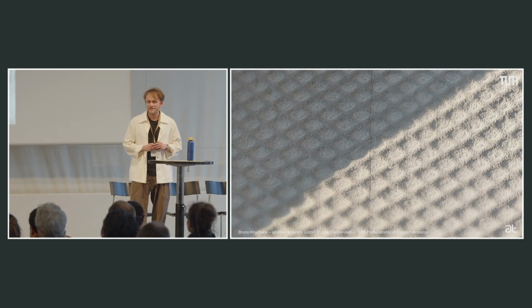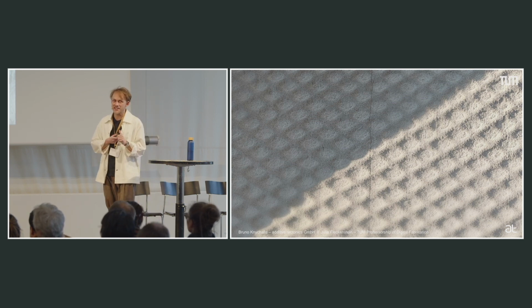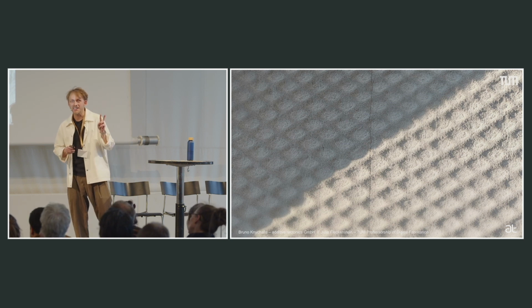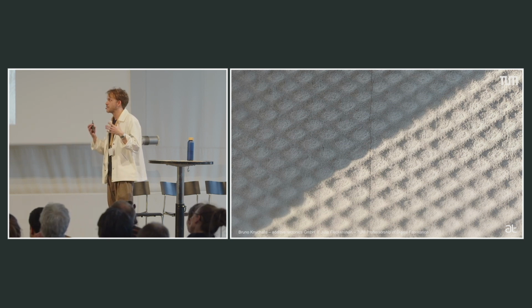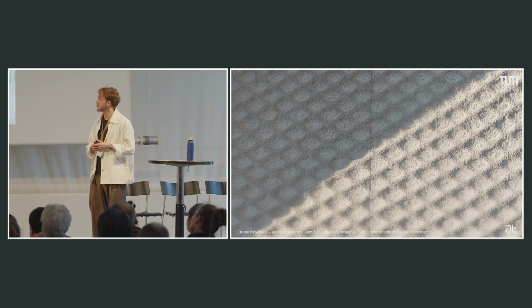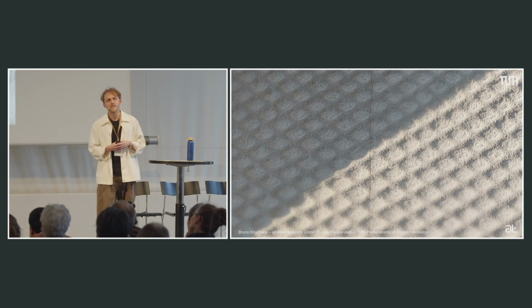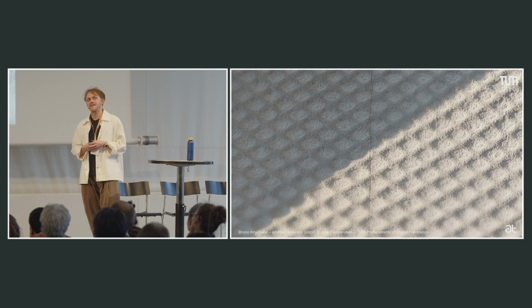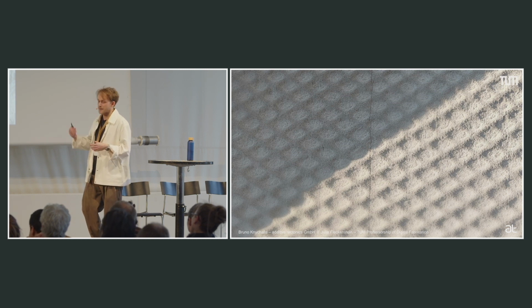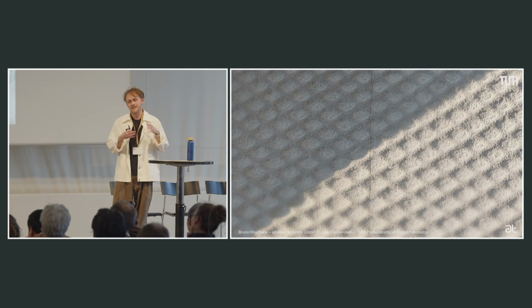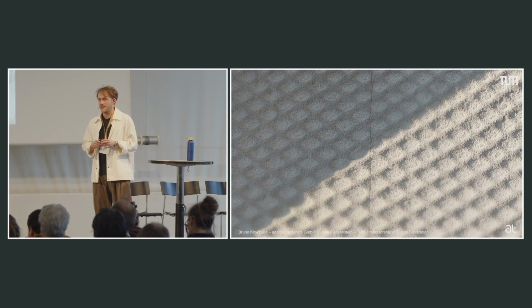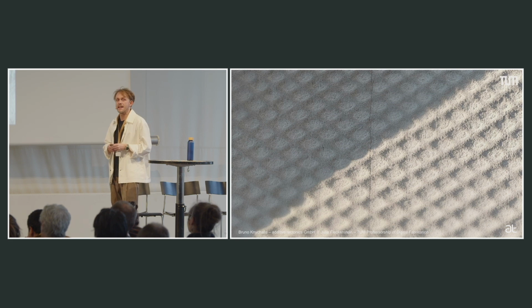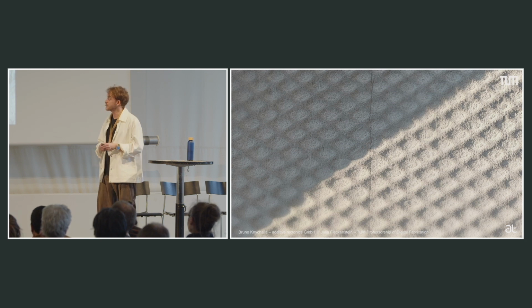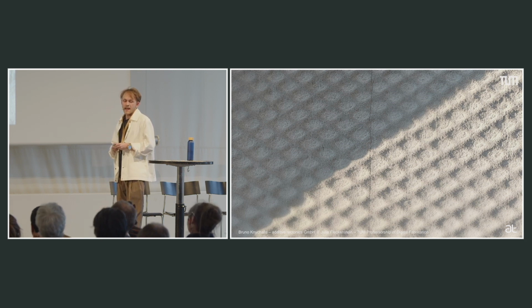Finally, cracking. We have 3 different types of cracking: hydration, shrinking, and part handling. Hydration and shrinking actually come from the same root. Both are based on the behavior of cement. If we use larger particles, we need less cement inside our parts, which means we have less cement that will shrink and that will also dry out. So by using a bit larger particles, I think we can handle these problems quite nicely. For the part handling cracks, it would be necessary or nice to integrate fibrous materials.